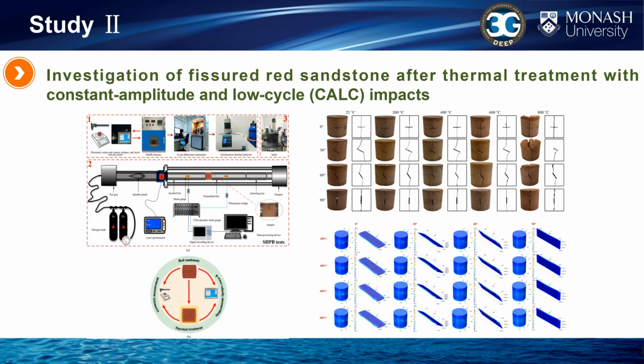In Study 2, we conducted an investigation of fissured red sandstone after thermal treatment with constant amplitude low cycle impacts. In this work, red sandstone samples after the same heat treatment as in previous studies were tested by XRD and STA respectively. The CALC impact tests were performed on the specimens using a modified split Hopkinson pressure bar, and the microscopic characteristics of the fracture surfaces of the specimens were examined using SEM.